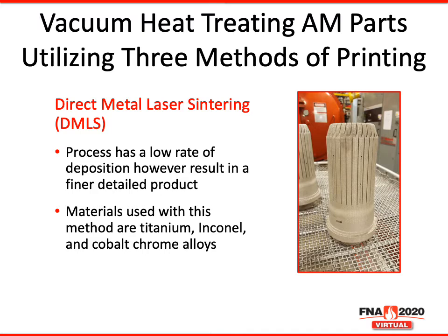So another picture here. This is another picture of direct metal laser sintering. This process has a low rate of deposition, however, it results in a finer, detailed product. The materials used with this method are titanium, Inconel, and cobalt chrome alloys. This particular part that you're looking at is a piece of Inconel 718 that was orbital welded. Now it's printed as one piece via this process, which would be 50 parts versus one piece. This is an oil and gas packer.